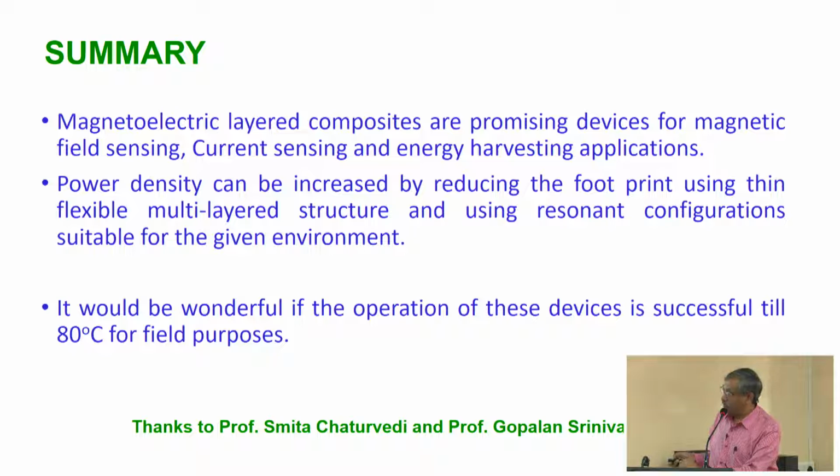Always assume that you are going to operate in a field of around 80 degrees centigrade or more. And not only ferroelectric materials, you can also use relaxor ferroelectric materials, which can have a large dielectric constant and are not affected much by large temperature variation. So that is another promising material people can utilize to make a device.